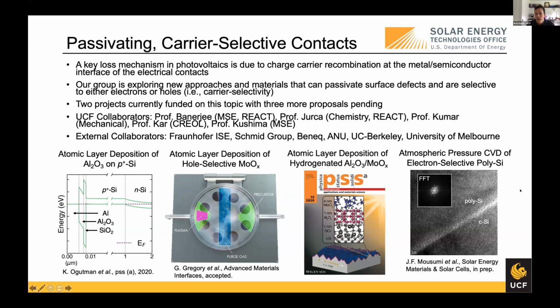More recently, I have a graduate student that's working with Schmid Group. They're a large equipment manufacturer, on an atmospheric pressure-based chemical vapor deposition process to deposit doped polysilicon. So in this case, we have a very thin silicon oxide layer that you can just grow chemically very easily in manufacturing. And then this atmospheric pressure thin film process doesn't require vacuums, very high throughput. And so this technology is of interest to a lot of companies right now. So we're pretty excited about that and just wrapping up a journal paper on this.